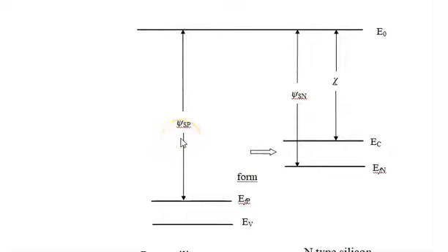And we know that for the Schottky barrier, the band bending is going to be equal to the difference in the work functions. For the Schottky barrier, this would be the work function of the metal. And if the work function of the metal is greater, as it is in this picture, than the work function for the silicon, electrons transfer from the silicon to, well, the left side, either the metal or the P-type silicon. And if it's a p-n junction, holes will transfer from the P side into the N side. And as that happens, the Fermi levels will become congruent.